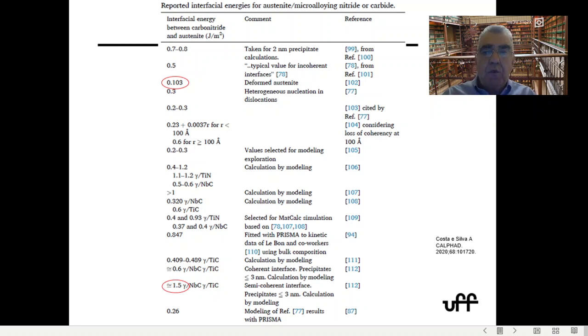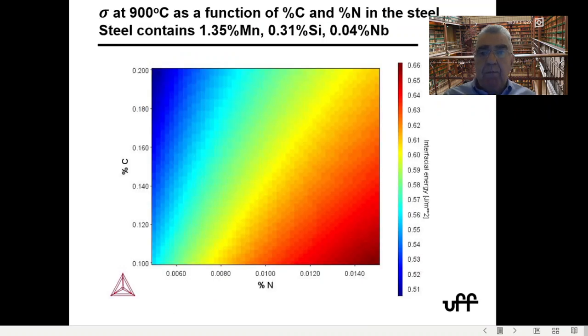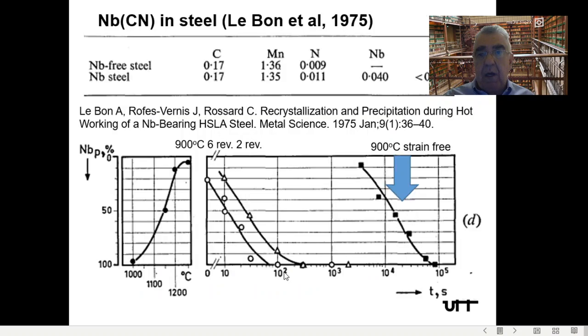And then worse than that, you can go in the literature and say, well, when you find that it was 0.4, you say, wow, this was according to this reference. And then you say, wow, fantastic, I solved my problem. So the new softwares now, they have models in which they calculate sigma as a function of temperature and composition. This is just a graph from Prisma that shows you how the sigma, from 0.51 to 0.66, varies at a given temperature just by varying nitrogen and carbon.